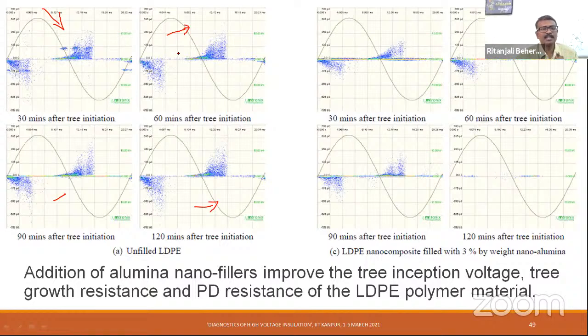In unfilled LDPE, we could see the partial discharge pulses are more in number, and the magnitude is also high, and the pattern also appeared to be broader. Whereas in the case of LDPE nanocomposites filled with 3 weight percentage, we could see all have been reduced. The number of pulses has reduced, the magnitude has been reduced, and the pulse density also has been reduced. And at 120 minutes, almost it has come down to a few pC, unlike in the other cases, which is about hundreds of pC. So this is the effect of nanofillers on the partial discharge. So this also appears to have a partial discharge resistance.